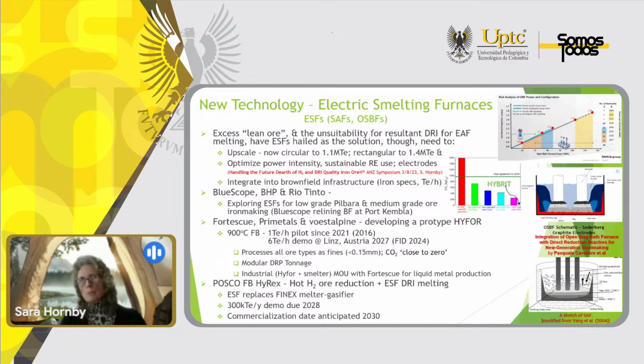One of the new technologies being looked at is this electric smelting furnace, ESF, which includes the submerged arc furnace and the open slag bath furnaces. They can take the lean ore and overcome the unsuitability for the resulting DRI, low-grade DRI, which would not apply to an EAF melting situation.